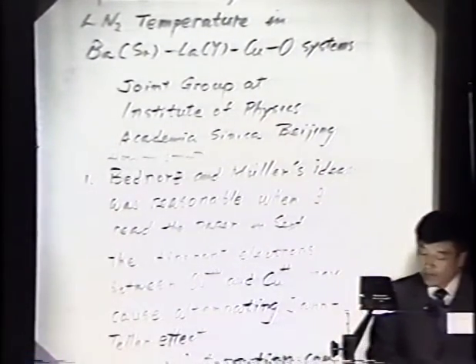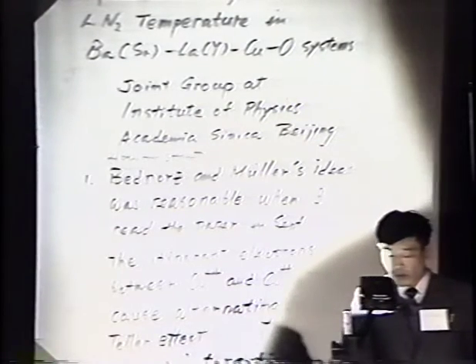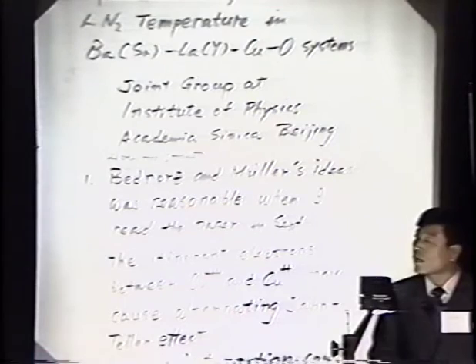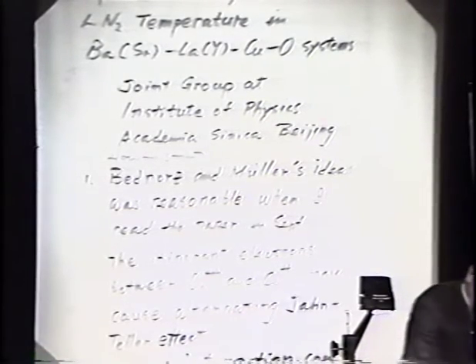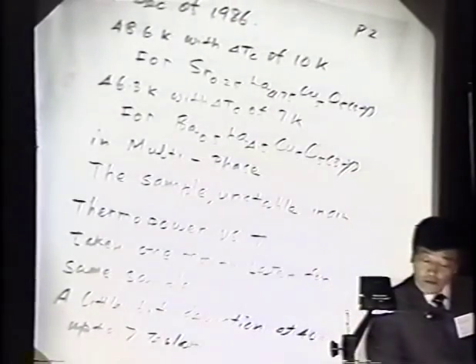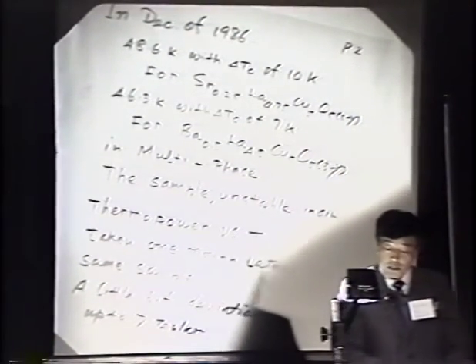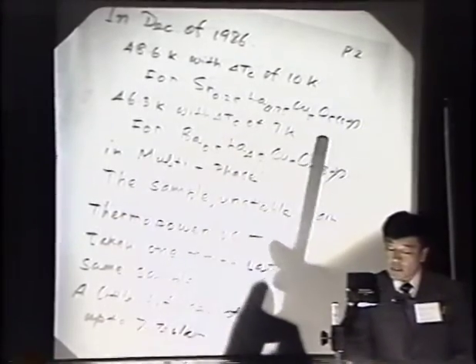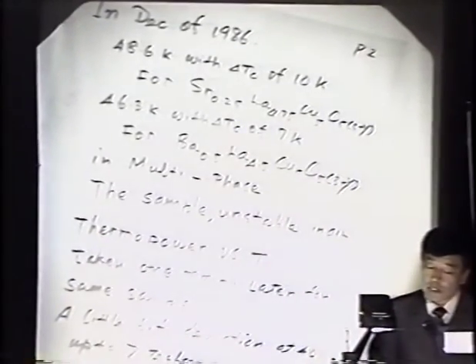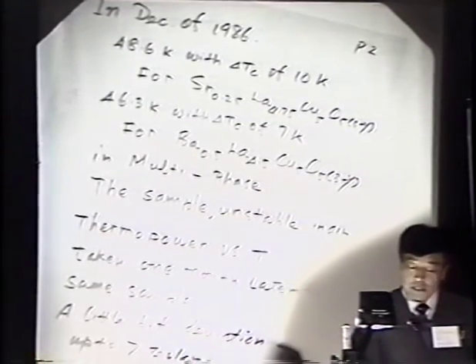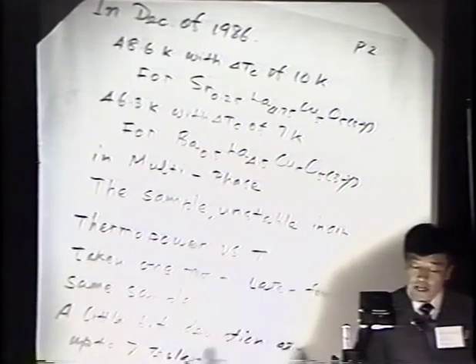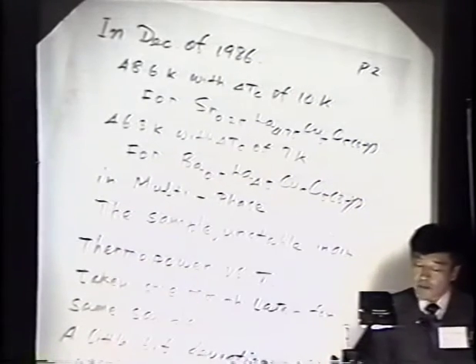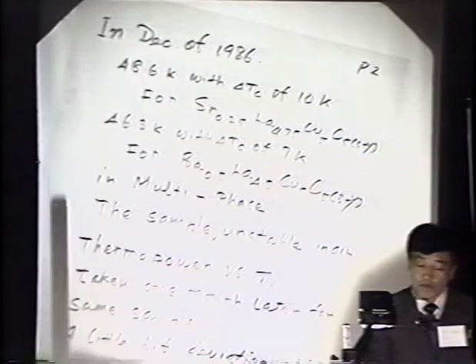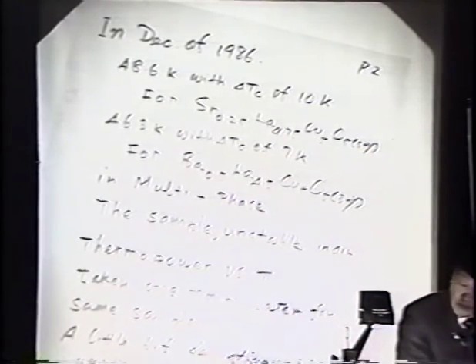I told this idea to my friends, and Professor Chen, who is also here, started to work in China. In December of 1986, in our experiments, we found in the strontium lanthanum copper oxide an onset critical temperature of 48.6 K, with delta TC of 10 K. And for the barium lanthanum copper oxide, the onset critical temperature was 46.3 K, with delta TC of 7 K.